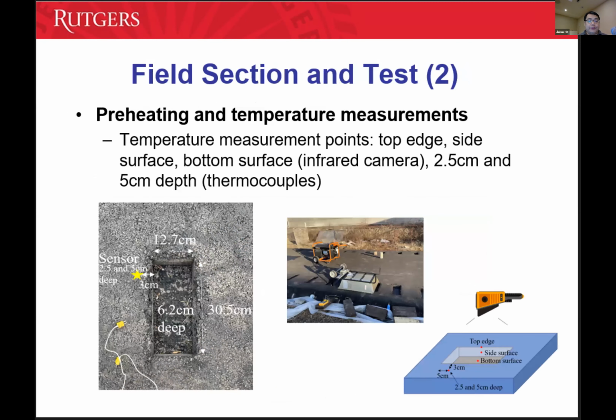So that's one of the artificial potholes we made. In that case, we conducted some trial heating. We did both infrared and microwave. As I mentioned before, microwave is a little slow in getting a higher temperature inside the pavement. But in this case, the pothole is pretty shallow, so infrared heating is more efficient.